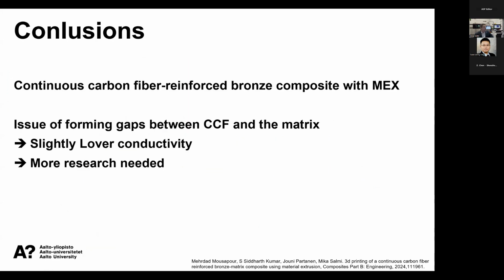So some conclusions. For this continuous carbon fiber bronze composite with material extrusion, there are some issues of forming gaps between the CCF and the matrix, and I think that will slightly lower the conductivity at this point. So there is actually a lot more research needed around this to see what we can really achieve with this.